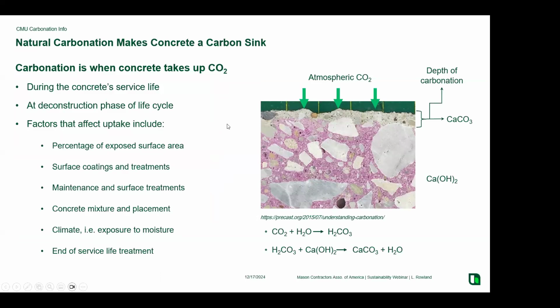Natural carbonation, here's another way to look at it. This is in a concrete system. Once again, if you recall, in the masonry unit, there's a tremendous amount of voids. In a standard concrete, essentially you're trying to eliminate your voids. You want to get it down to where there's essentially no voids. And you can actually put a dye on the concrete, and as the concrete carbonates, as the CO2 is absorbed, the dye changes color. So you can see just on the surface of a traditional concrete is where that carbonation depth happens. That's where the CO2 reacts with the free calcium and becomes CaCO3 in that process.